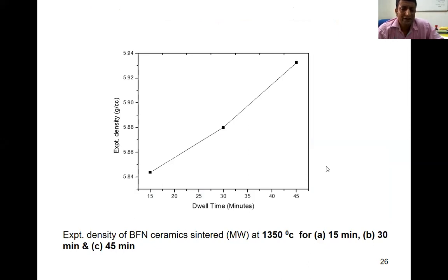The density increases with the increase of the time. When we increase the time durations, as I told, we have gone for 1 hour, but 1 hour for microwave processing is too high, and melting started inside the material actually. But we obtained the same density as we obtained by the conventional heating.